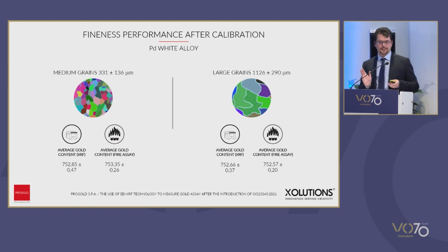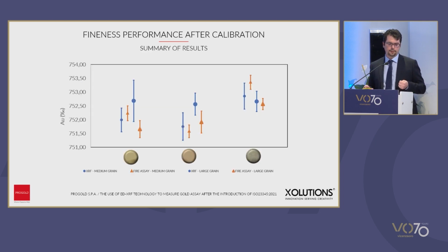So we could also think that the results in this case are even better. And the limit of fire assay for palladium is that palladium doesn't dissolve so easily, and so you have to take that into consideration. Here you see a diagram of what I just said, and you see that apart from the first case of yellow gold, there is always a good correspondence between the fineness achieved with the fire assay and with X-ray. So the performance of this technique for the alloys considered and for these measurements is very good.